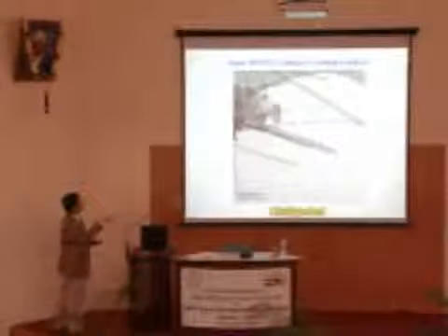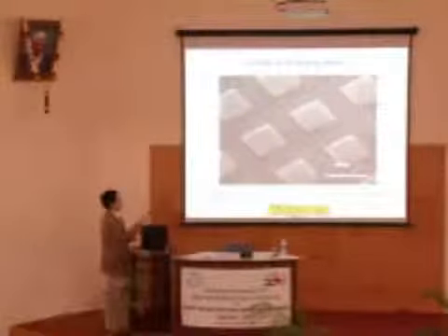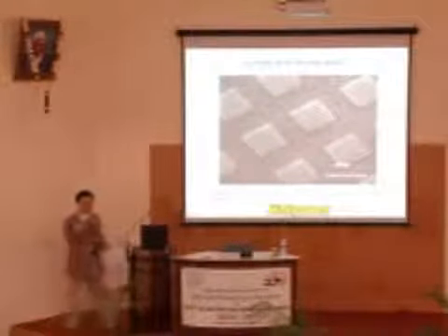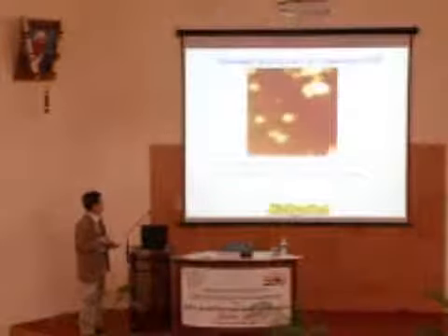Quickly, you can see the fine structure of the long-range order of the graphitic shell, and you can see that there's no catalyst on the substrate. You can go back here, there's no catalyst. It's perfectly clean. And you can pattern them to grow at the spot that you want. And just for the characterization, we proved that the band gap is about 4.4 to 4.9 electron volts, pretty stable for most of the tubes.